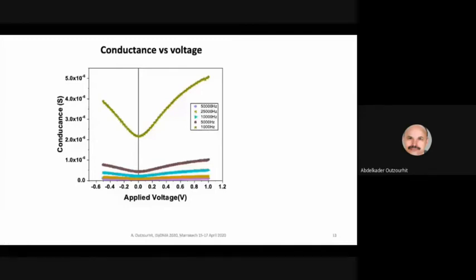And this is maybe attributed to the existence of those mid-gap states, which are finding it difficult to respond to the modulating signal that is used for the measurement. This we can see more clearly in the measurements that were performed using the capacitance as a function of frequency in this figure here.